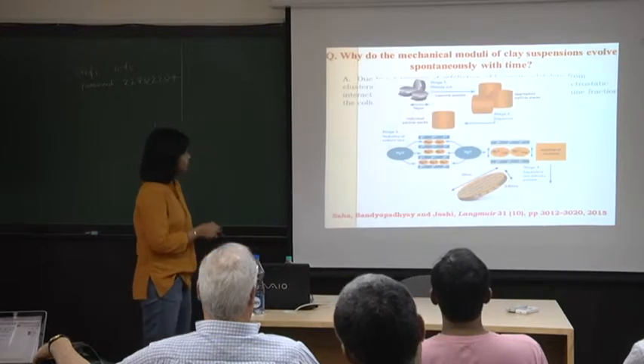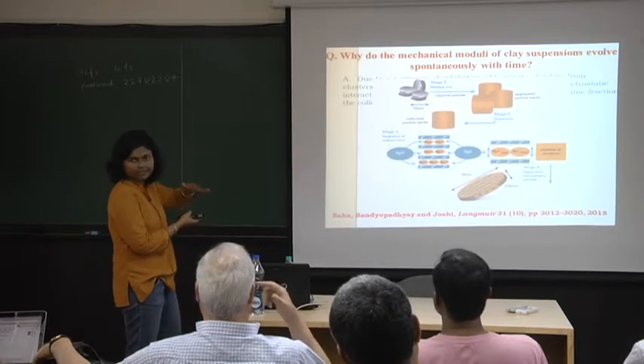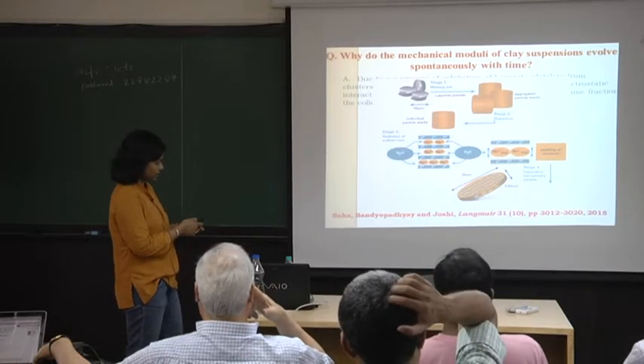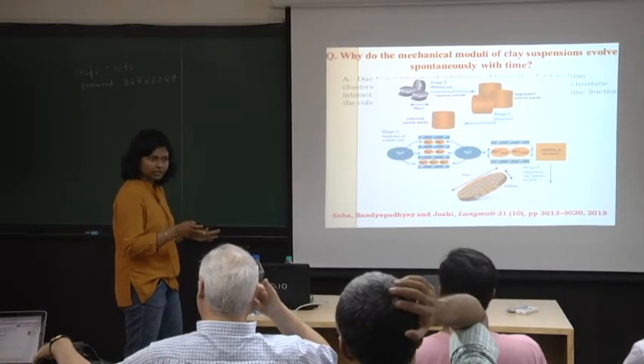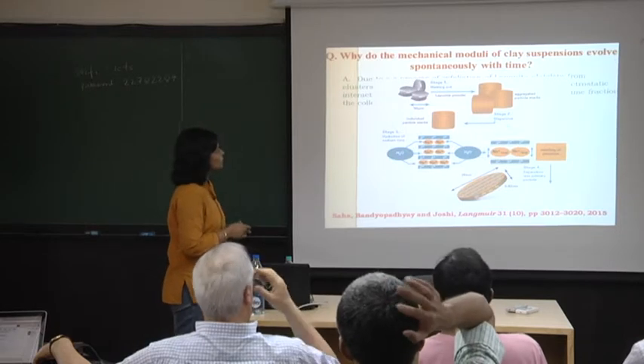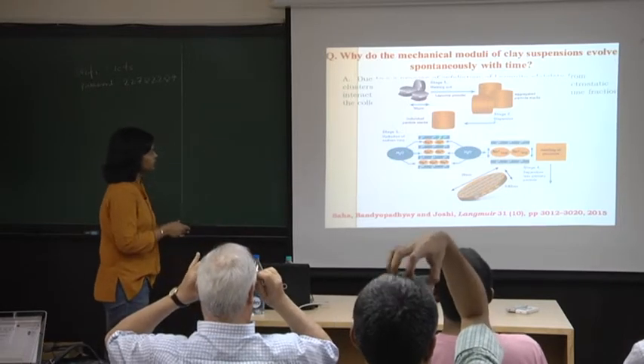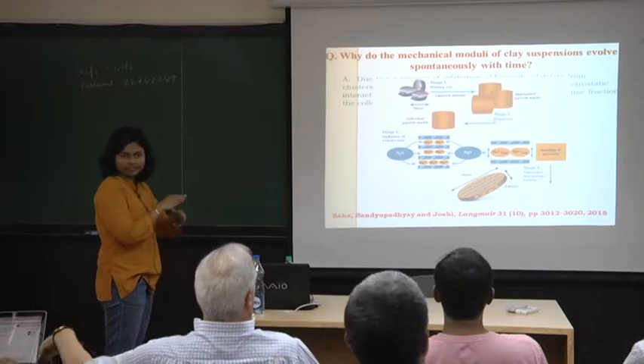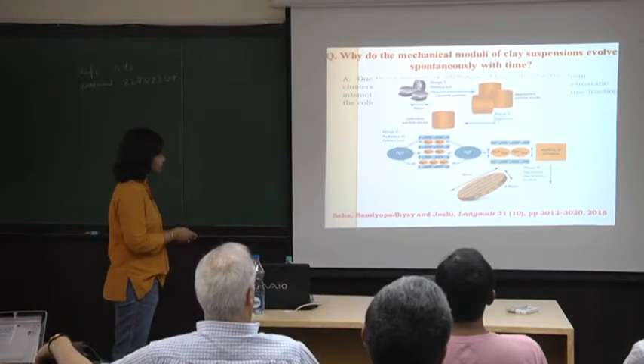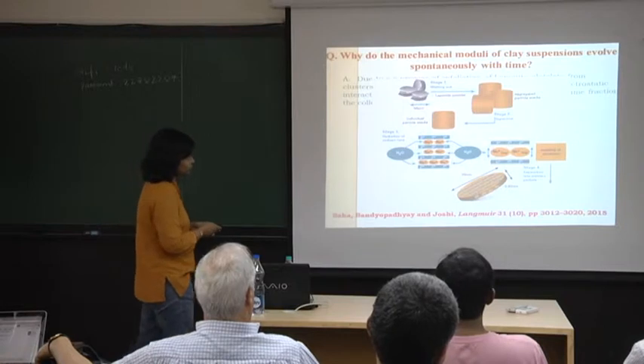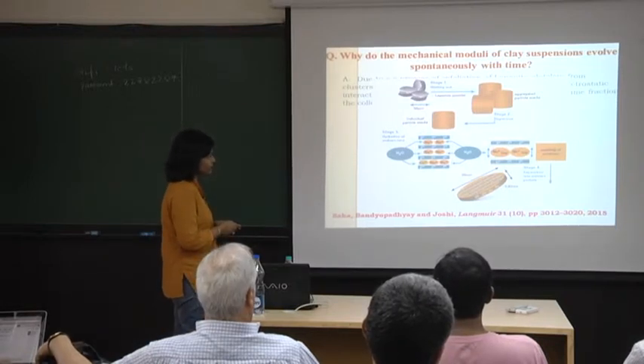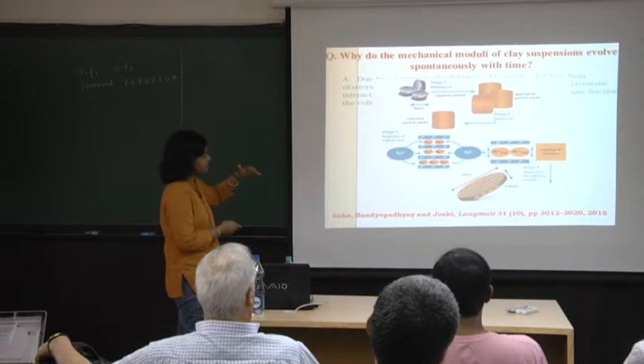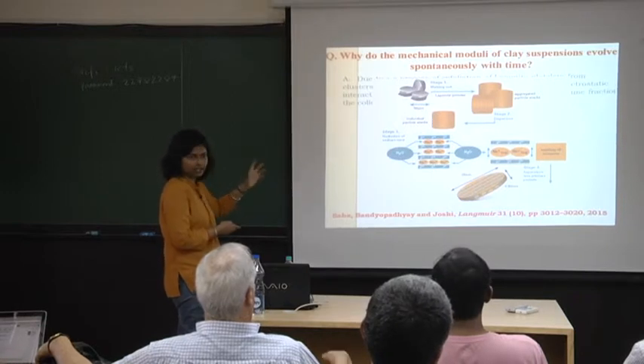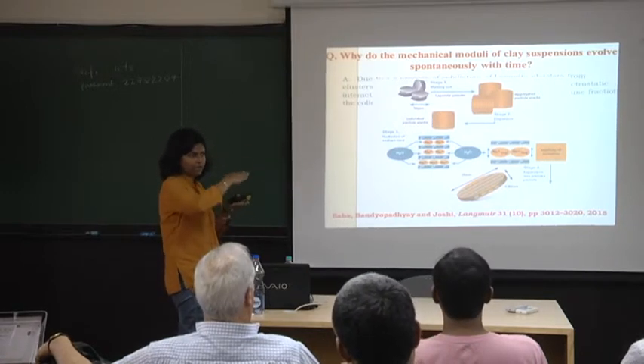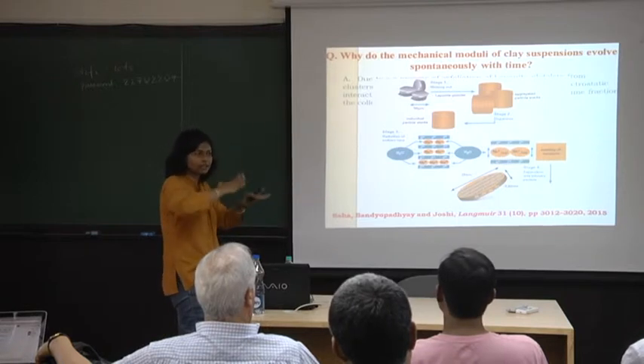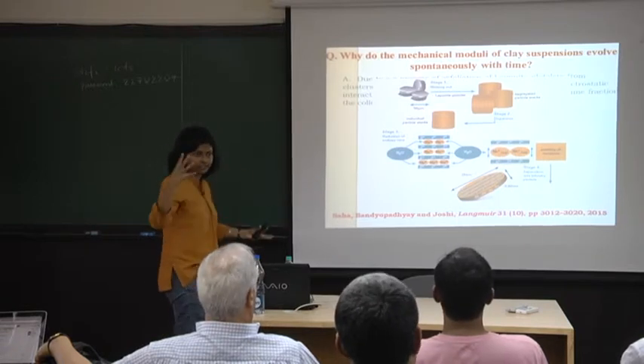So this is what clay looks like. In the dry form, it's basically stacks of particles like this. These are called tactoids. Smarajit, everything okay? You're looking worried. Okay. So these are aggregated particle stacks. When you disperse them in water, the aggregated particle stacks start forming single particle stacks. And when you put them in water, there were always sodium ions in the interlayer galleries. So now they start getting hydrated. They apply an osmotic pressure, and it starts prying the tactoid apart. So the tactoid swells.